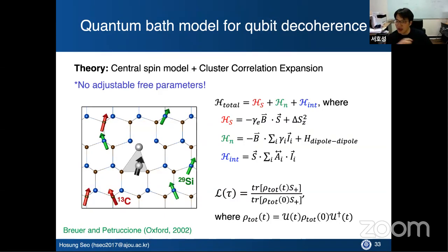And in this sample, we don't have many electron spins nearby from other paramagnetic defects. But if your sample is dirty enough, with lots of dislocations or vacancies or dangling bonds, things like that, then you have lots of electron spins in a bath, and those electron spins basically dominate the decoherence problem. But in this sample, the sample was clean. There is a negligible amount of electron spins, paramagnetic defects, and we cool down the sample to sufficiently low temperature to remove the electron-phonon effect. Then the leftover is the nuclear spins, which is an intrinsic factor in the material.